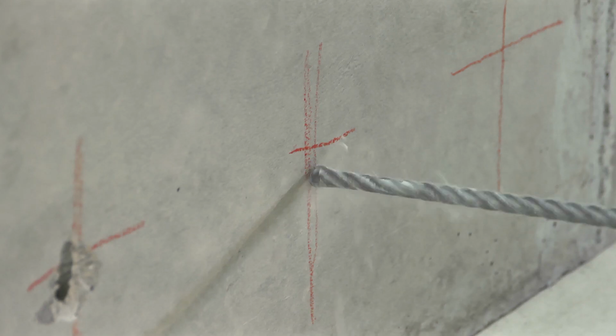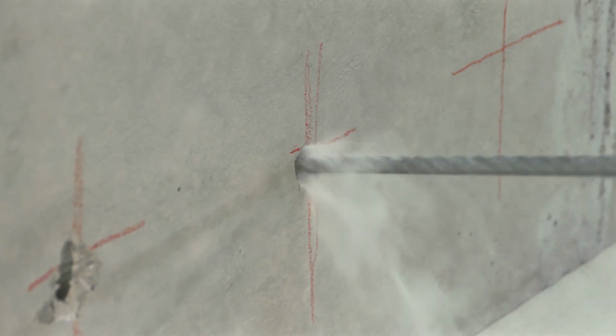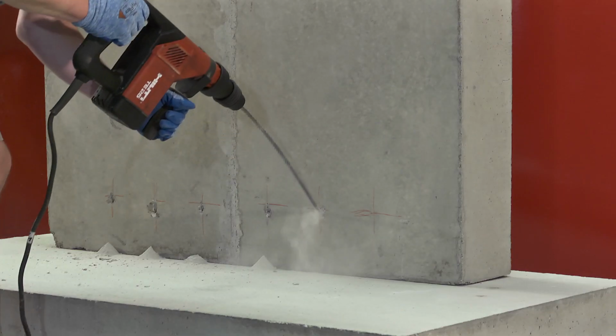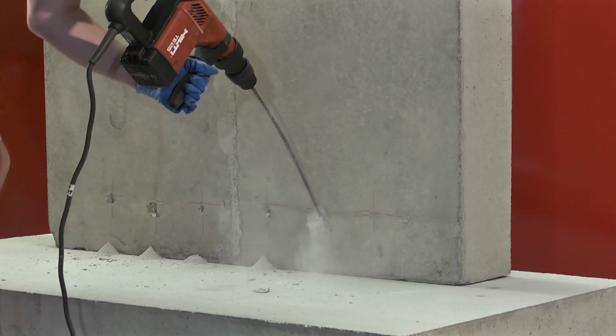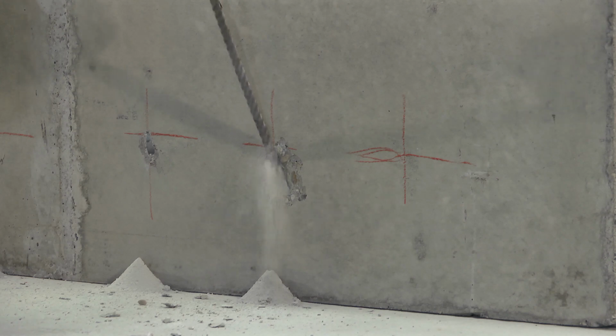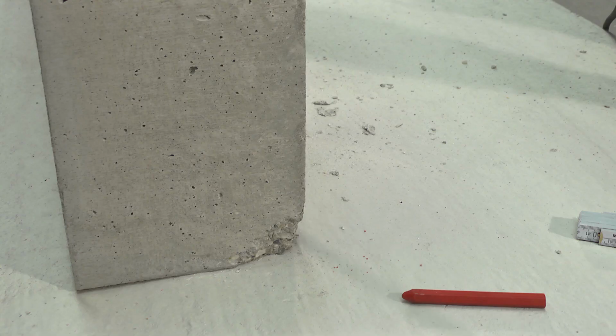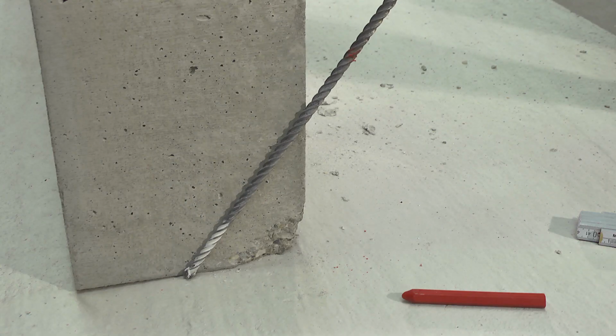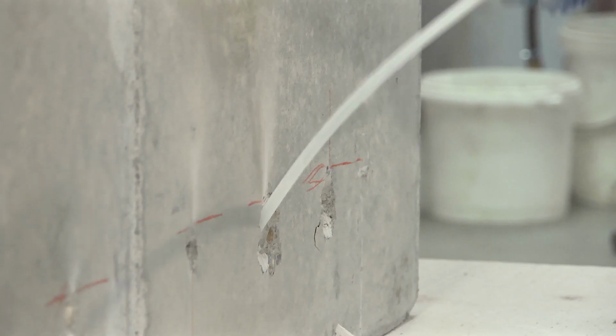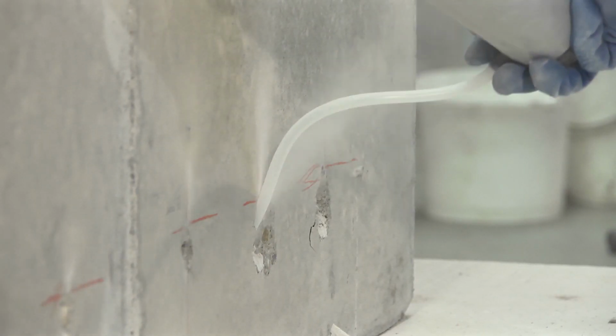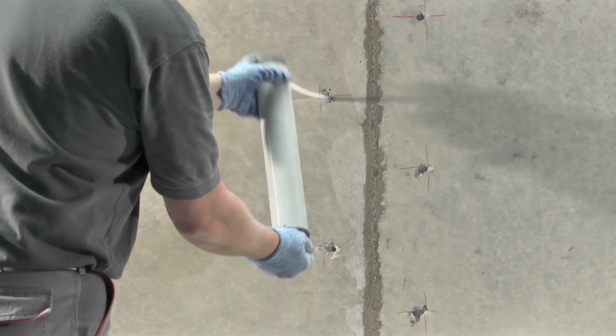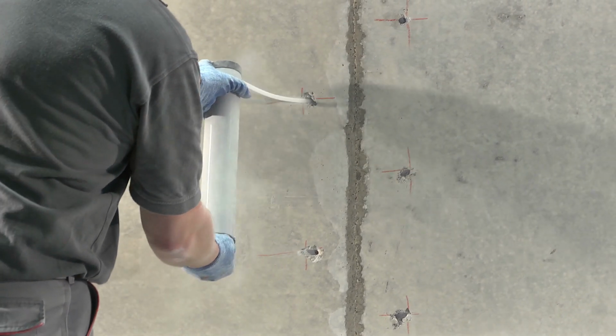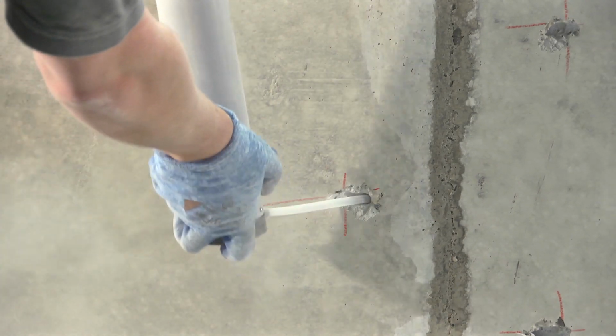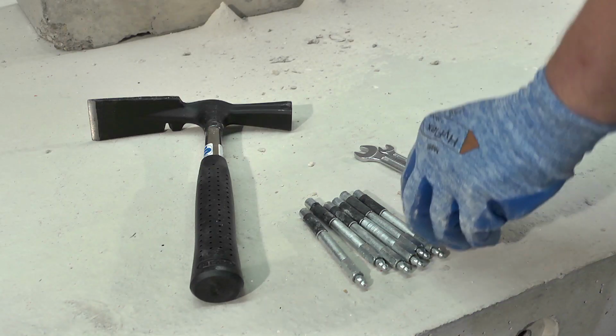Continue to drill towards the joint center. It is essential that the drill hole penetrates the crack or joint. Therefore, the depth of the drilled hole should exceed the theoretical depth by at least 50 millimeters. After completion of drilling, clean any debris from the drilled holes using compressed air. This is a key step, since it will ensure secure anchorage of the packer during installation.